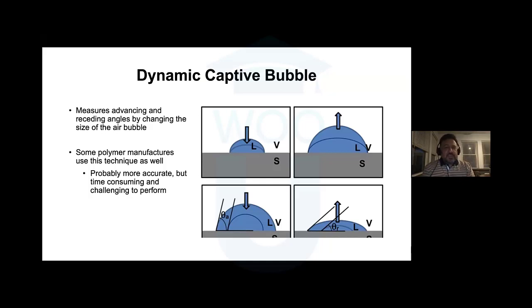A third way of doing this that's similar, it's the captive bubble method, but a little different way of doing it is a dynamic captive bubble. And you'll see this sometimes reported in laboratories or polymer companies spec sheets. They'll talk about their wetting angle by the dynamic captive bubble. And this is a similar procedure, but we're actually putting air down and then pulling the air back up again. So it's kind of like it's dropping the air and then sucking it back up again, back and forth, and watching how it changes the size of the air bubble as it advances, and then it recedes back again into the instrument that drops that bubble out. Again, more accurate yet more time consuming and increasingly challenging to perform.